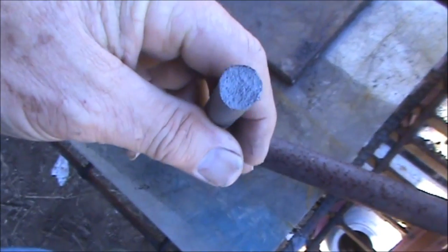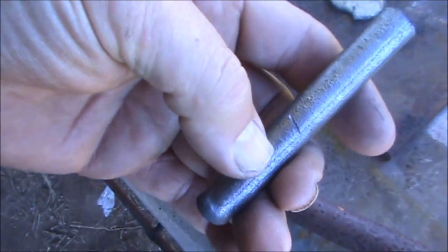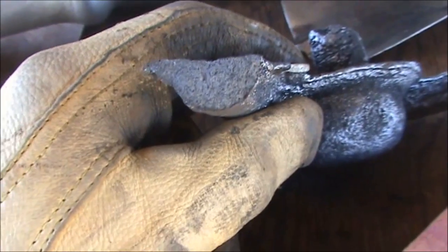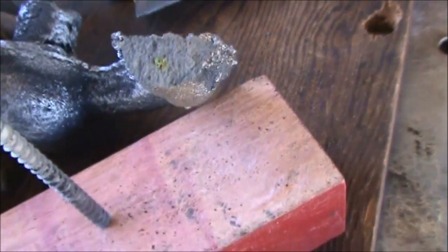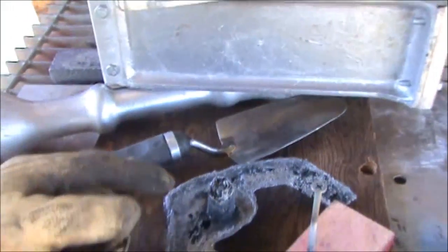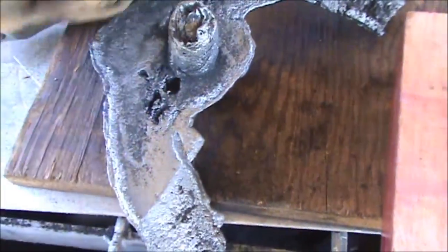Did get some good iron. This was a little riser piece — nice grain structure, more of a vent than anything else. Sawed into it with a hacksaw right there. This was the gate where it broke off — nice clean iron, gray, no silver around the edge or anything. There's a spot that looks like slag on it right there. You can tell it ran out because it had already come up about six inches. I'm not pouring fast enough I guess, and it's sucking air. I haven't figured that out yet.